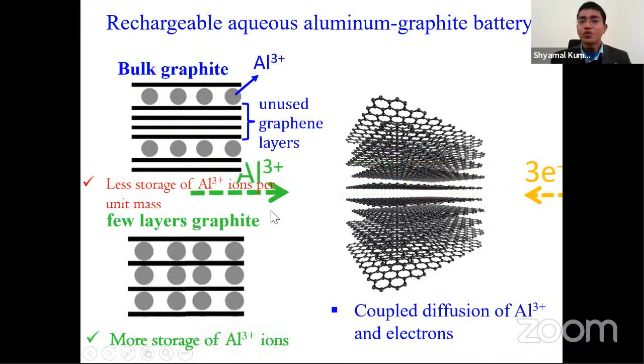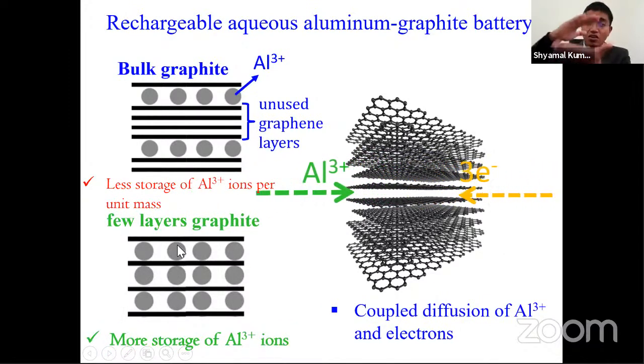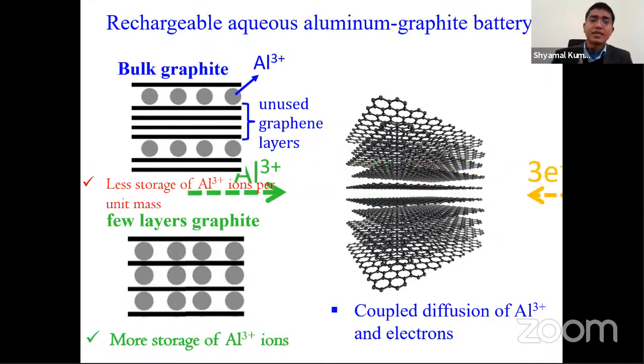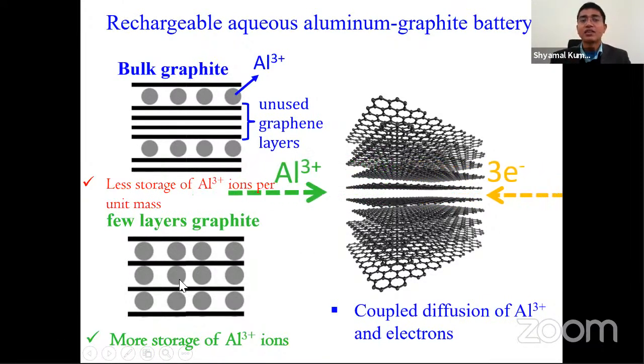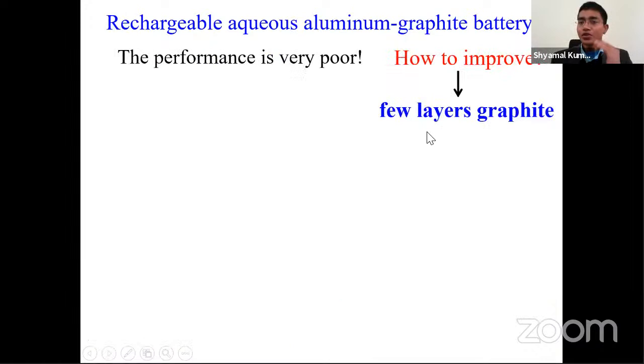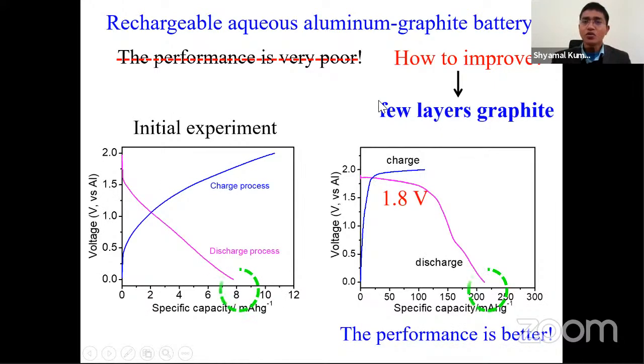On the other hand, if we use few layer graphite, let us say only 4 or 5 layers, then all the aluminum ions can access all the graphene layers available in that graphite. So more storage of aluminum ions. So we realized that if we use few layer graphite, then we may be able to improve the performance. And it is really so. When we performed the experiment with few layer graphite, we saw a dramatic difference compared to our initial experiment. Initially, we got only 8 milliampere hour per gram. Now we got 200 milliampere hour per gram. Not only that, we could achieve 1.8 volt for the battery. This is a very remarkable result so far as aluminum graphite is concerned.